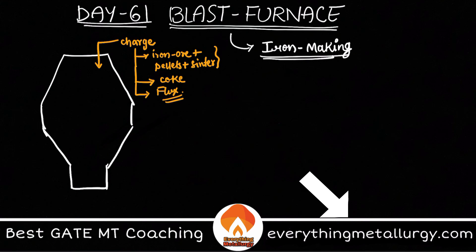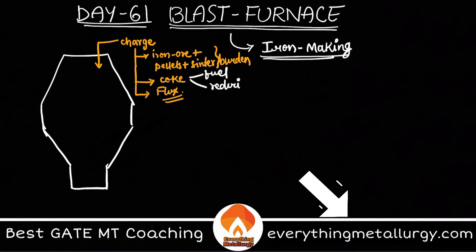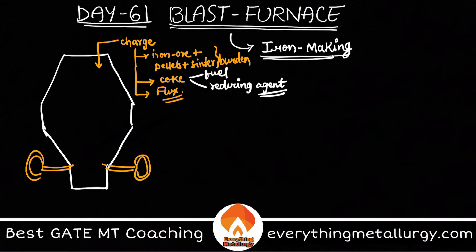Coke has various functions: it meets the thermal and chemical requirements, meaning it acts as a fuel and as a reducing agent. Coke will combust with the help of preheated air. Preheated air is injected inside using something called tuyeres — the tuyeres are the pipes which are inserted into the blast furnace.